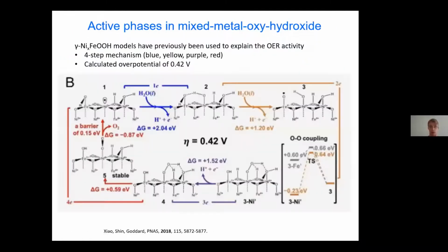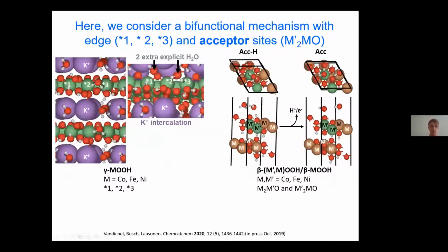But suppose we use now the bifunctional mechanism. So we start with gamma metal oxyhydroxides, where we have potassium intercalation and water intercalation. And we combine these gamma metal oxyhydroxides with what we call beta metal oxyhydroxides. They don't have any intercalation. They're just layered. And most of the metal sites are here 2+, while here they are 3+, or a bit higher than 3+, because of the potassium intercalation, which is not completely charge compensating.